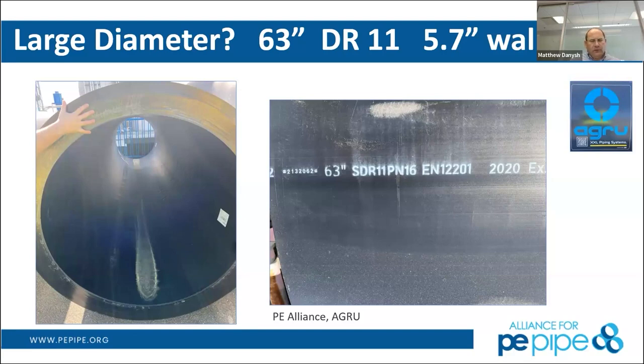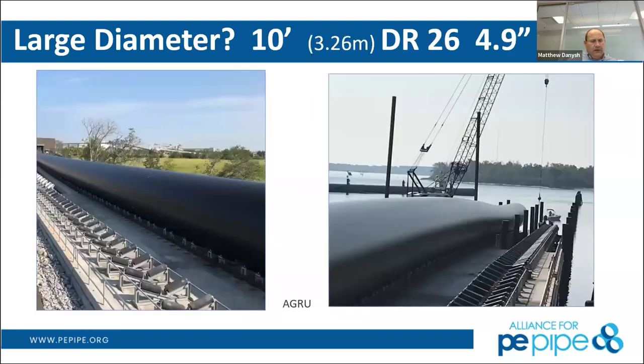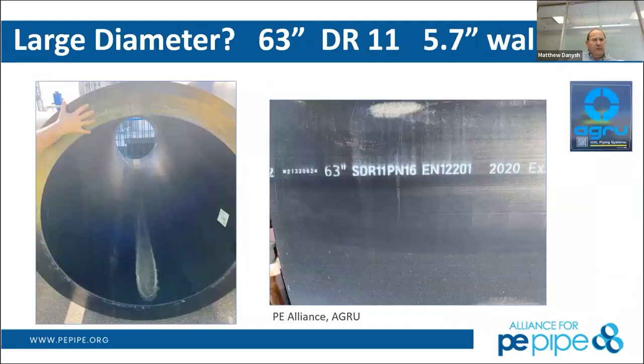Since the Hazen-Williams formula is used for friction head loss, if you backtrack that formula from flow into the diameter, you end up with a situation where as you increase the diameter, your flow increases not linearly, it's more exponentially. If you do the math, it's a 2.63 power of the diameter increase in flow. That's the reason why larger diameter pipes are much more beneficial in large flow situations, because if you parallel smaller pipes together, you end up with more frictional loss, more material, and more pumping cost.